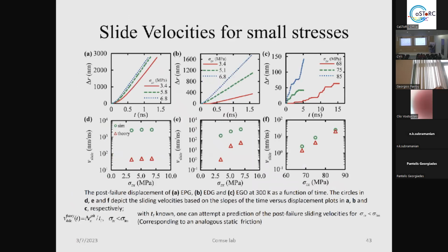Now, for stresses which are smaller than the sigma lim, one can also calculate the sliding velocities, as we can see here. For the three different systems, the first is for the EPG, the EDG, and the EGO. And of course, we see here in terms of physics, again, the difference of adhesiveness. We have a very poor adhesiveness, almost zero. And that's why you can see that the graphene comes out with almost zero stress. And that's why the simulation calculations contrast with theories, they're having this error. We saw that due to the very smooth and clean surface, the graphene somehow swims, let's say. So the adhesiveness is zero.